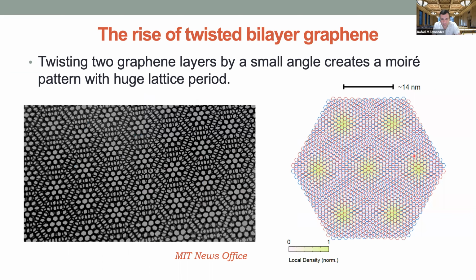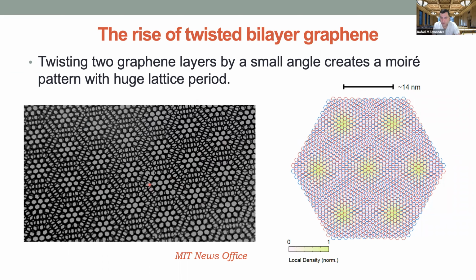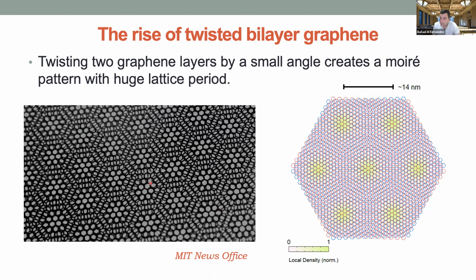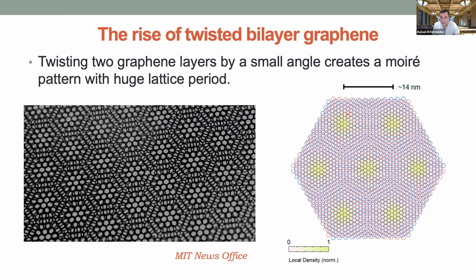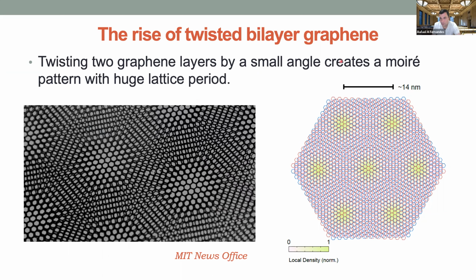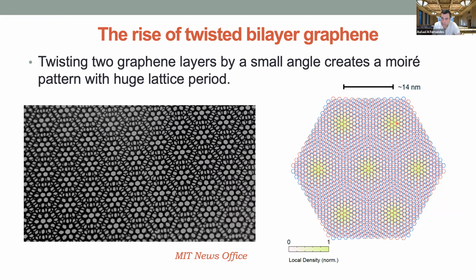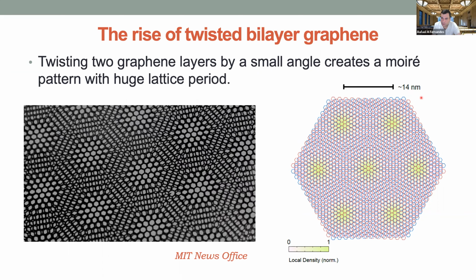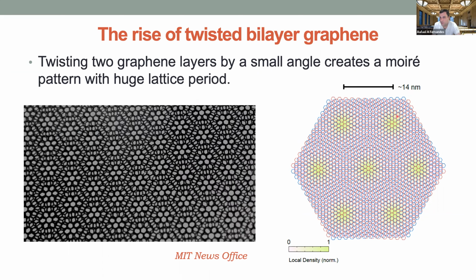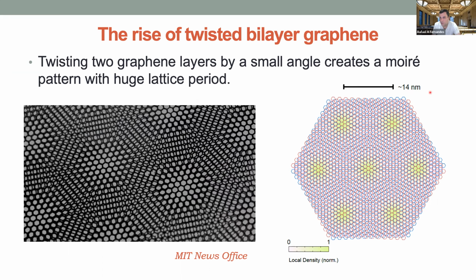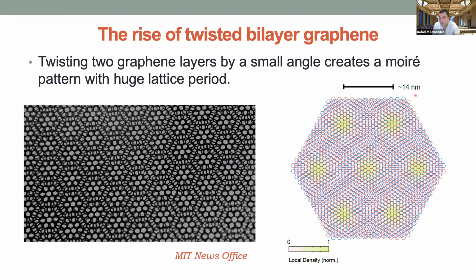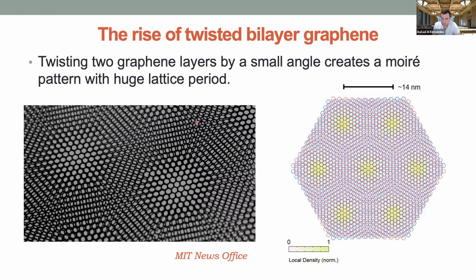If you take two graphene layers and twist one with respect to the other by a small angle, you create a superlattice that is called a Moire pattern, or Moire superlattice. And if this angle is small, the separation between the period of this Moire superlattice is huge. For example, here's 14 nanometers, which is 100 times the carbon-carbon distance in graphene.